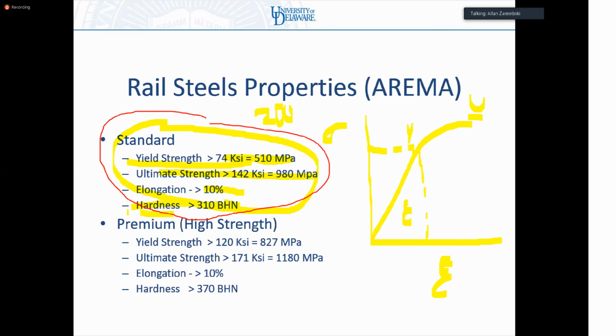Now, if I look at premium rail, the yield strength is up to about 800 megapascals, and the ultimate strength is closer to 1,200 megapascals. The elongation is still about 10% because we want to have that amount of ductility. And the hardness is up to about 370 BHN. So the hardness is about 60 points higher than standard steel.